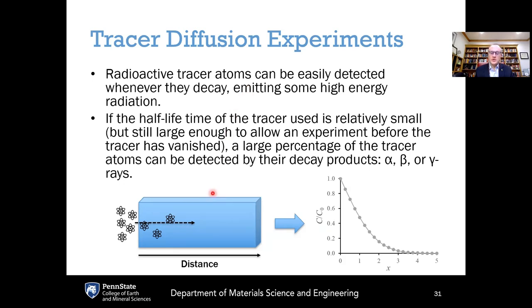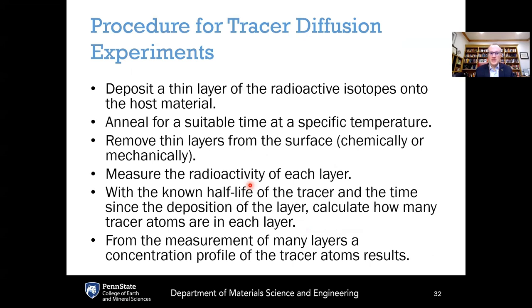But it's important to choose the half-life of the tracer that is short enough that you can observe it on the time scale of your experiment, but long enough that it doesn't undergo complete decay before you have a chance to measure it. So the key thing here is really picking out an appropriate radioactive isotope with a half-life that is on a suitable time scale for the experiment.